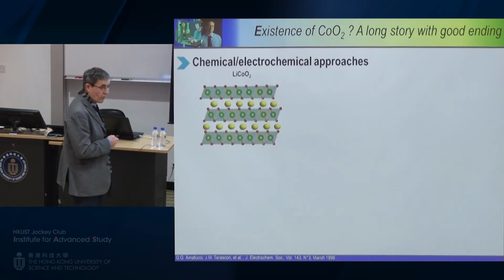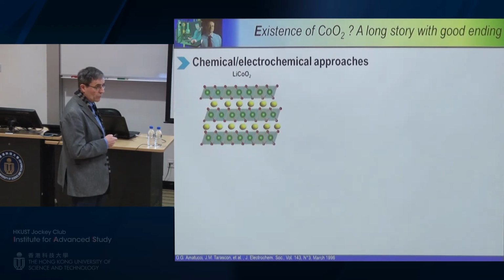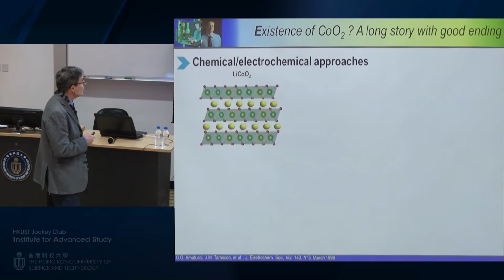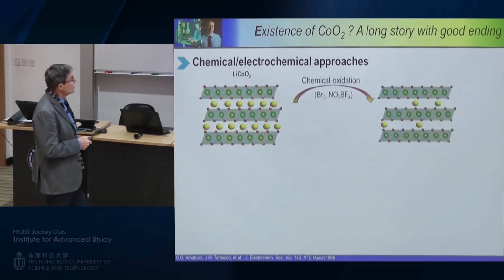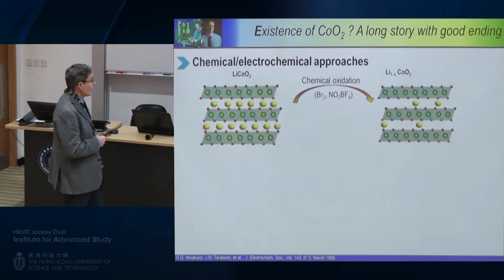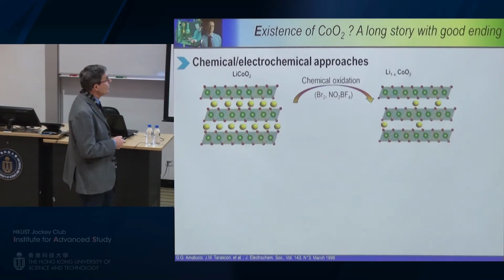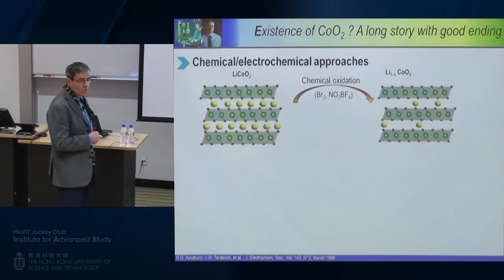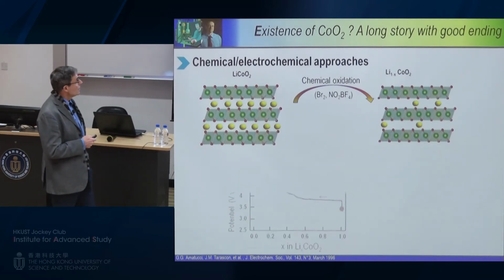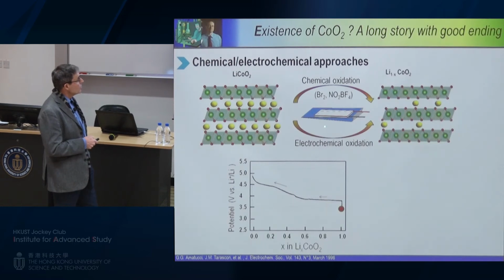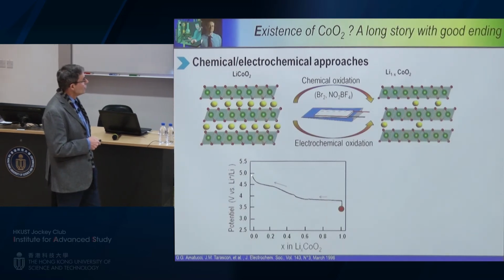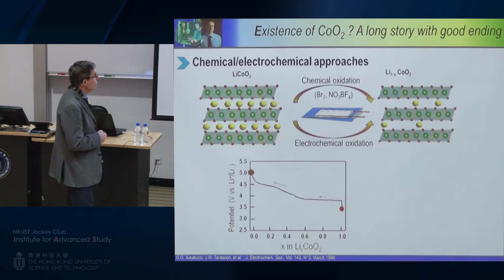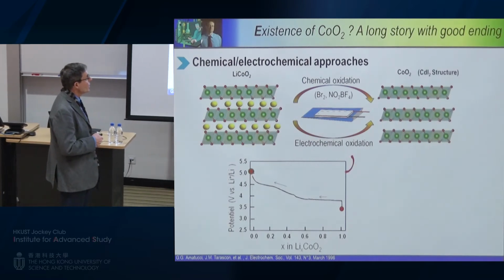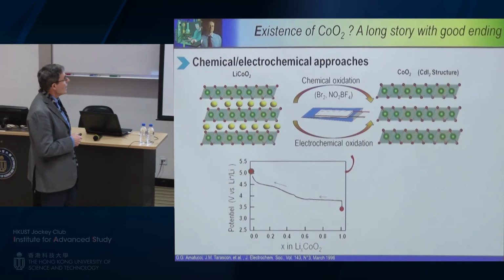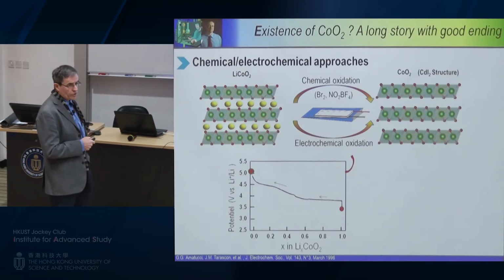And this was a big dilemma for about several years, where theorists were telling us, you won't be able to do it and so on. Anyway, if you do it by chemical reaction using bromine or NO2BF4 as oxidative agent, we were never able to remove all the lithium from the structure. But when we came out with this plastic technology, we could now go to about 5 volts. And when we do this, we were now able to remove all the lithium from the structure, as you can see here, and move from a normal R-3m structure to a CdI2 structure.